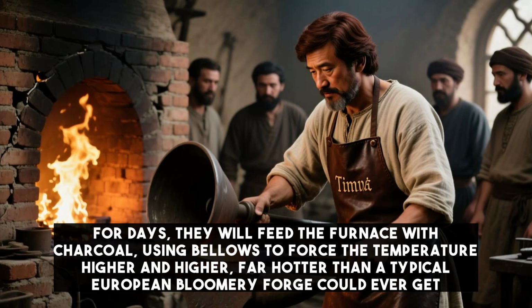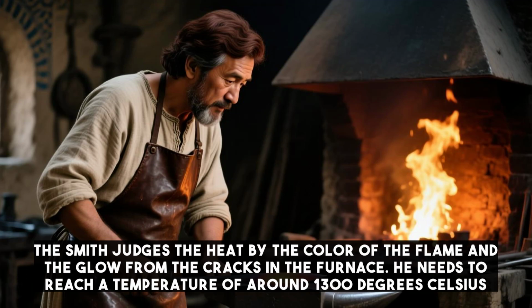For days, they will feed the furnace with charcoal, using bellows to force the temperature higher and higher, far hotter than a typical European bloomery forge could ever get. The smith judges the heat by the color of the flame and the glow from the cracks in the furnace. He needs to reach a temperature of around 1300 degrees Celsius.